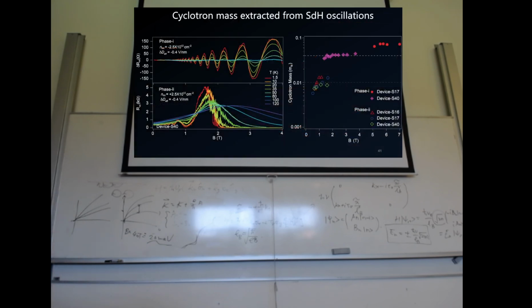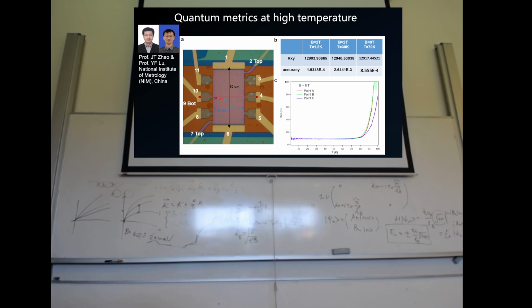And this is also proven by the SdH oscillations experiment. For example, if you measure this conventional phase SdH, the quantum oscillations disappear at a temperature of about 40 Kelvin. But in the new phase, where supposedly we have this electronic crystal, the oscillations are preserved at 120 Kelvin. So everything is in agreement. That's how we understand the system.